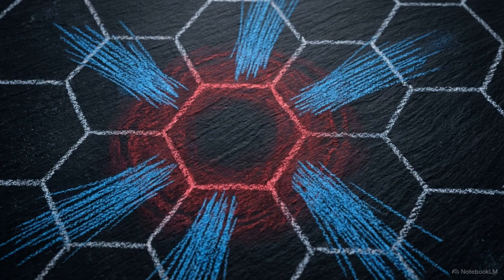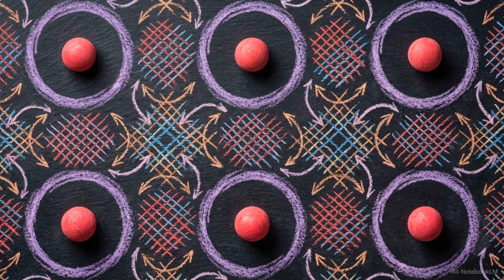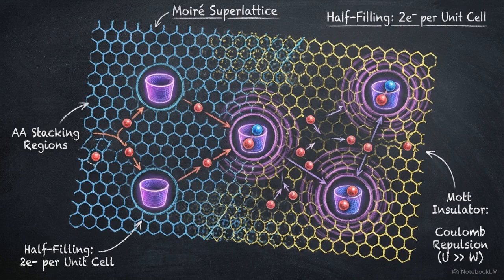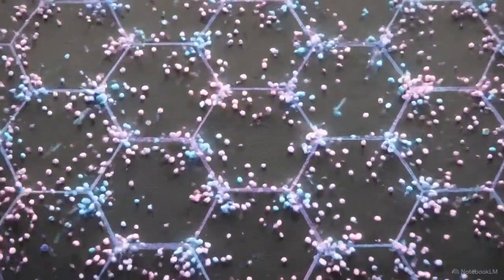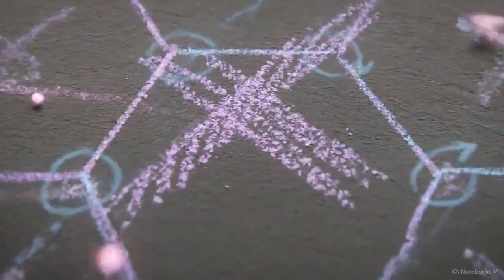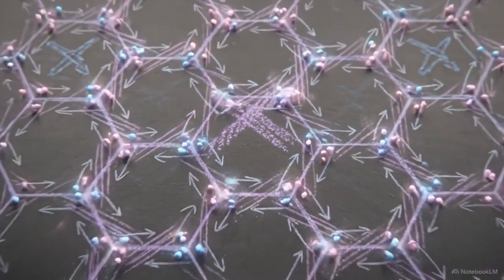By removing the kinetic energy, the 1.1 degree angle flips the balance of power inside the material, leaving it governed by new forces. With kinetic energy gone, the repulsive Coulomb interactions between electrons take over the entire system. Electrons begin to cluster in concentrated circular zones within the Moiré pattern, avoiding the regions between them. This leads to half-filling, the moment two electrons occupy each unit cell of the superlattice. Their mutual repulsion prevents any adjacent particles from moving. This repulsion creates a Mott-like insulator. The pristine conductor becomes a quantum traffic jam driven by electron interaction.